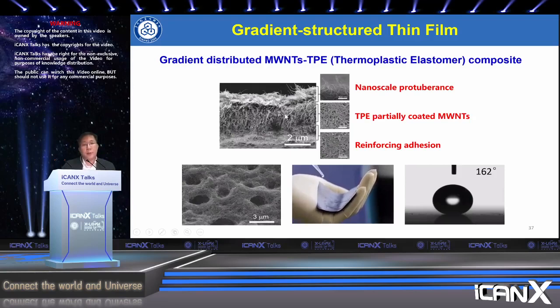About a few micrometers thick of the composite films, you can see that on the top there are micro holes of these structures, and also on the top there's nanoscale protuberance at the surface. In the middle there's thermoplastic elastomer partially coated with the carbon nanotubes, which is very sensitive to the strain sensing. And at the bottom there's more thermoplastic elastomer, so it can reinforce the adhesion with the substrate.